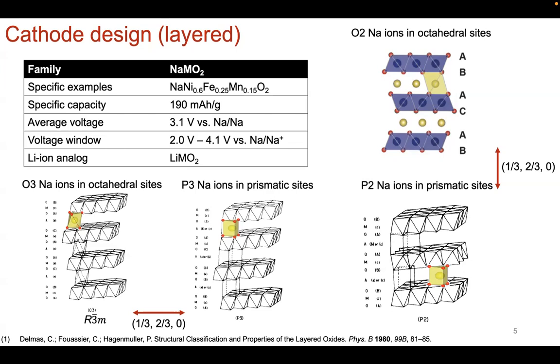So if the sodium ions are sitting in octahedral sites that you see here in this layered structure, where this is the metal oxide, and then this is the layer in which sodium ions will occupy, if they sit in octahedral sites that you see here, then it is an O3 type structure. But if the sodiums are sitting in the prismatic site that you see here, then it'll be denoted as a P3 site.